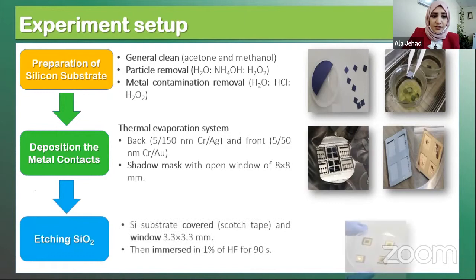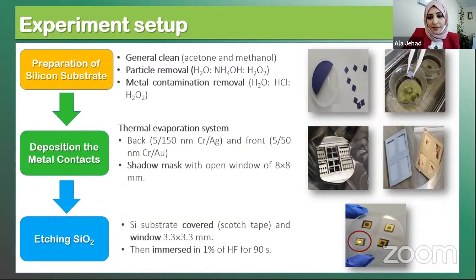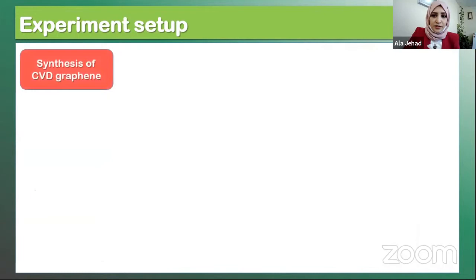Next step was etching silicon dioxide. You can see in the image, we covered the solar cell with a Scotch tape, and then we open a small area, almost 3.3 times 3.3 millimeter, and then we etch the silicon dioxide chemically using 1% of HF for 90 seconds. And then wash the substrate and dry it with nitrogen.